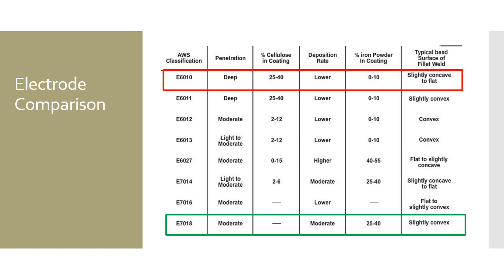Deposition rates. Well, E6010 has a really low deposition rate, but you're not using it for its deposition rate. You're using it because it's a fast freeze electrode. It would be like drying concrete that you always see in the movies, right? The concrete that dries in like 2 minutes. Well, similar. It's a fast freeze electrode. It freezes really quick, which allows you to weld open roots with it and do a lot of things that you can't do with other electrodes.